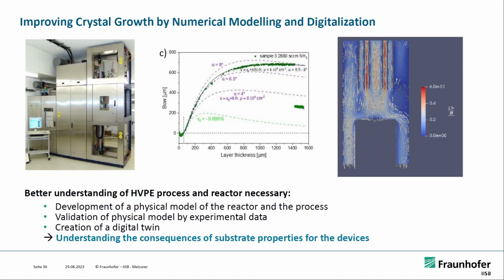So here you see, for example, a continuous bowing curve over the radius versus thickness, which reflects the process time, so the growing thickness of the layer. And you see that the crystal starts bowing. With a model of how the crystal really grows, from the nitrogen fluxes and from the temperature field that you implement in the physical model, you can simulate such curves and better understand what your process is generating, react more intuitively, and eventually understand the consequences for substrate properties and failures, and better understand the growth process.